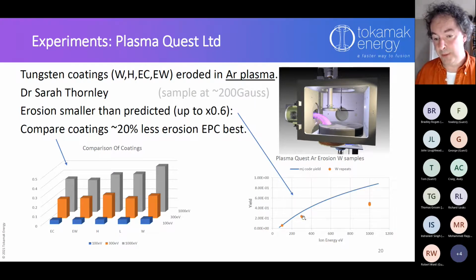So that could be what's happening here. I've been doing a bit of modeling on that, and it looks like it might add up. In which case, that's good news for us, because it means that the actual erosion we see in a magnetized environment will be less than the prediction from this blue line, which is good, better than the other way around.